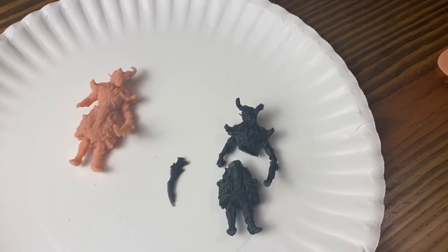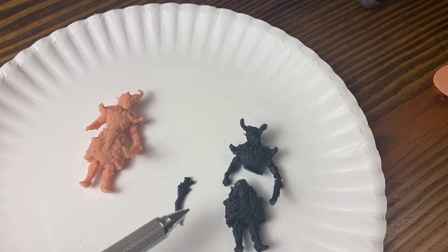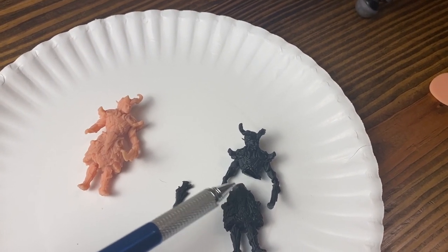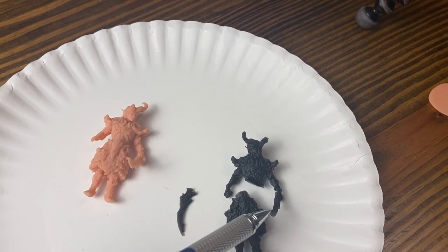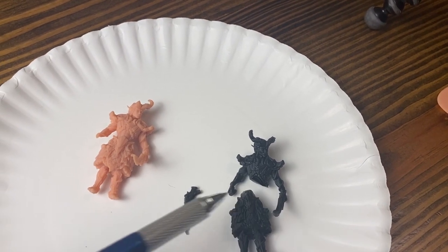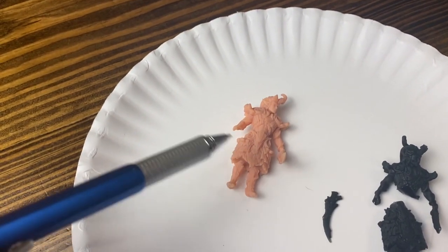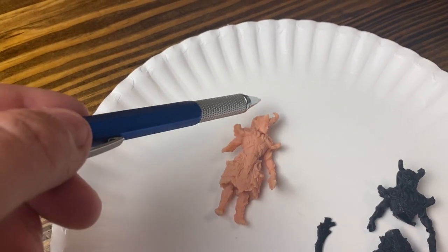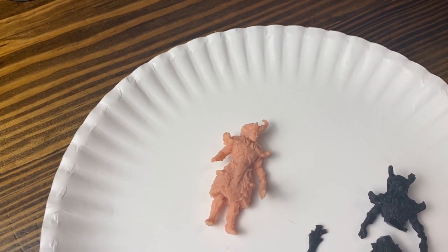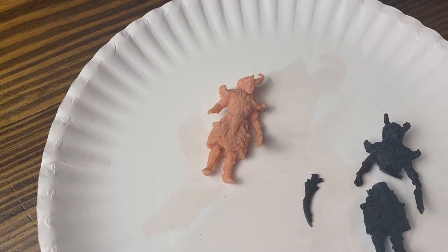As you can see, both models sustained damage in the fall, but I would say that the damage to the standard resin model is much more complete and catastrophic than the model printed in the ABS resin. I think I can definitively say that in this impact test, the round is won by the ABS-like resin.